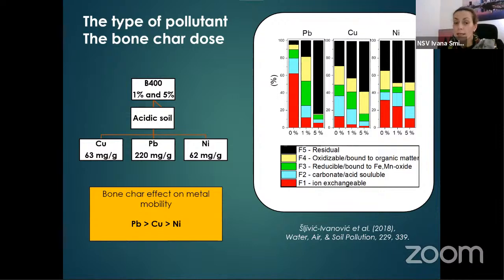The bone char was added at different amounts of 1 and 5% into an acidic soil, which had simultaneously elevated concentrations of copper, lead, and nickel. After 2 months of incubation of this soil with bone char, we performed a sequential extraction analysis, and we revealed the distribution of metals in the original soil and after implementing the various doses of the bone char.